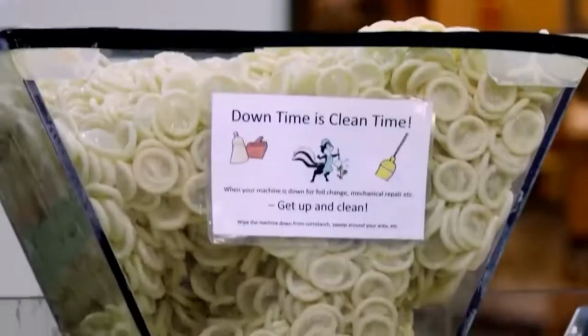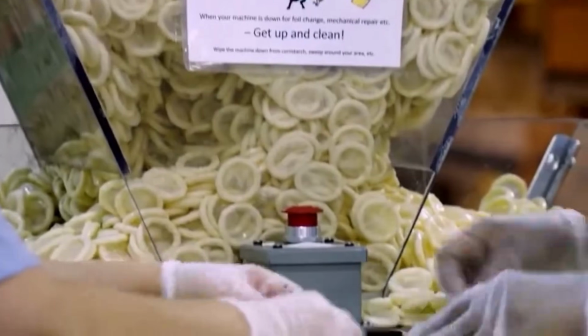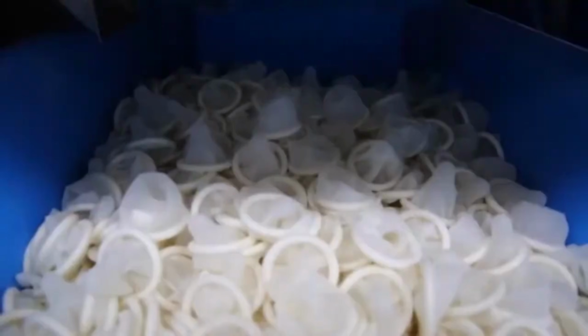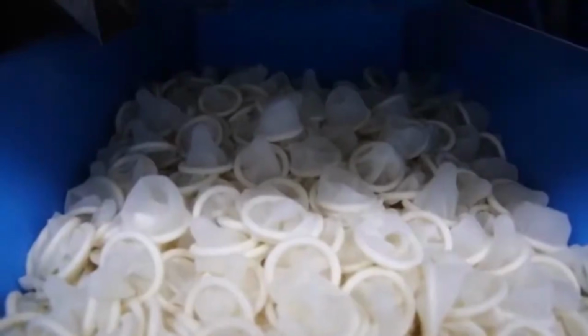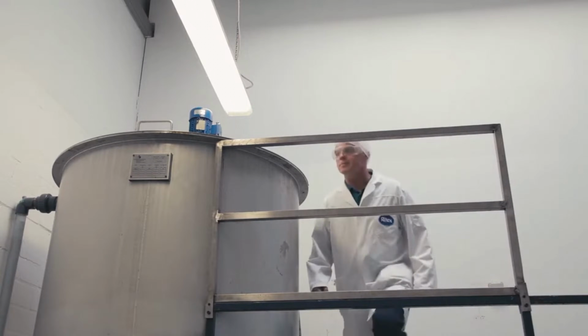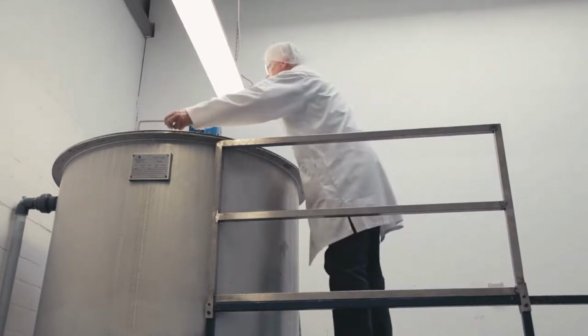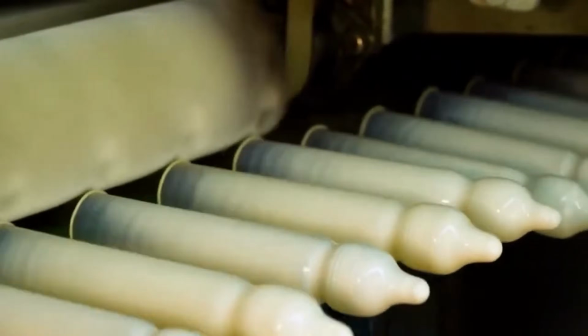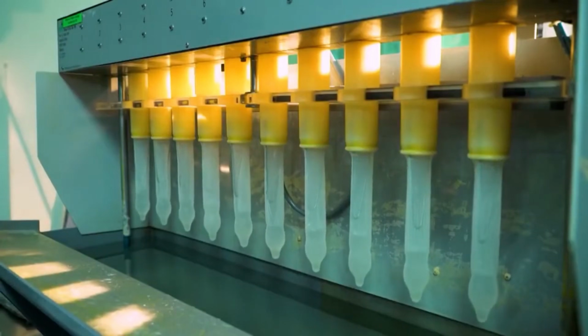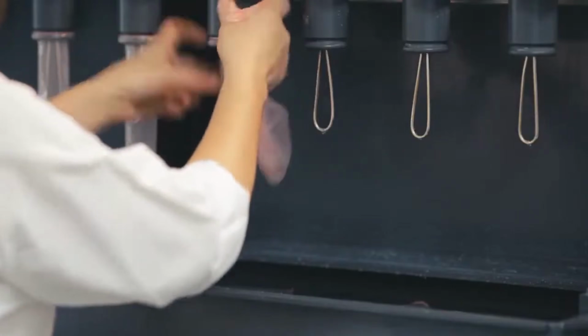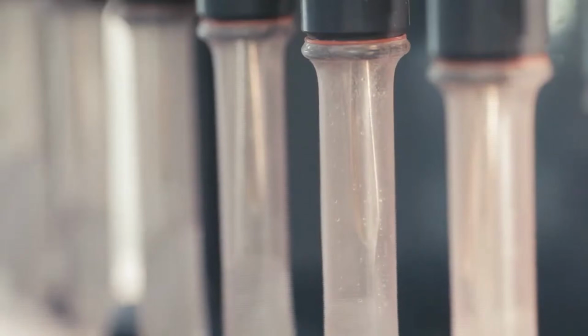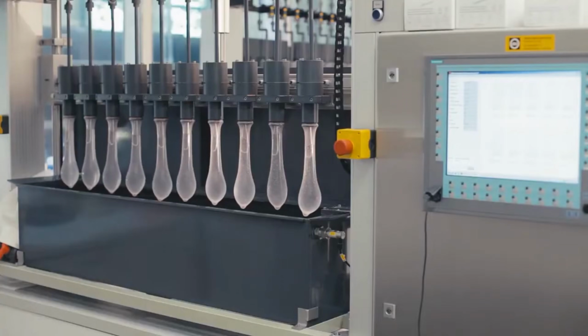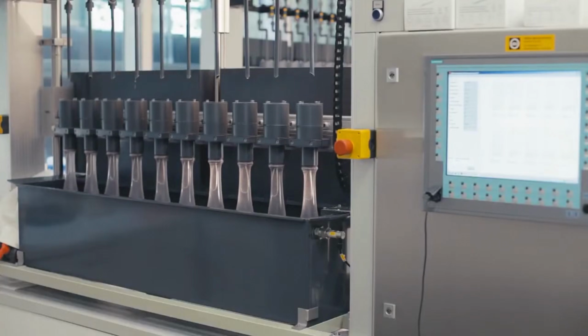After dipping, the latex-coated formers pass through drying and curing ovens. Heat causes the latex particles to bond together in a process called vulcanization, transforming the liquid coating into elastic rubber. Temperature and exposure time are tightly regulated to achieve the correct balance of strength and flexibility. If curing is incomplete, condoms may tear easily. If overcured, they become brittle. Sensors continuously monitor oven conditions to maintain consistency across tens of thousands of units moving through the line. Once cured, the condoms are no longer liquid, but they're still attached to the formers.